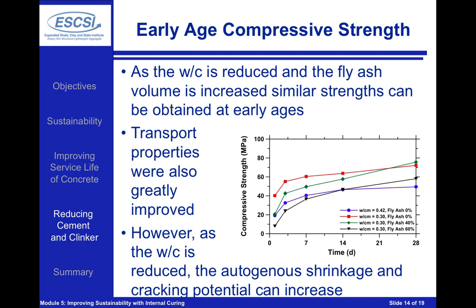So to really start to take a look at this, we can look at the early age compressive strength when we alter our water to cement ratio. So our 0.42 reference mixture is shown here in blue. And what we can see is that we'll go from a compressive strength of about 20 MPa at 1 day up to about 35 or 37 MPa at 7 days. And if we were to just reduce the water to cement ratio of our system, going from a 0.42 to a 0.30, we can see ourselves shifting from that blue line up to that red line, where we're seeing a substantial improvement in strength. We might be doubling the strength at the first day. We might be going from about 35 MPa up to about 60 MPa at 7 days. So just altering the water to cement ratio does exactly what we would have expected it to do, reduces our porosity and increases our strength.